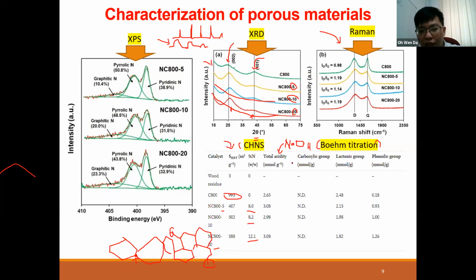And you also can look into carboxylic group, lactonic group, and phenolic group. So for all this, you have to change your base. For total acidity, we use sodium hydroxide. For carboxylic acid, lactonic group, or phenolic group, we use something else, maybe like sodium carbonate, and so on. So we use something else with a different strength, different basicity. NaOH is a very strong base. That's why we use it to neutralize all the acidic group on the adsorbent. So you can choose other things, and from there you can deduce what are the amount of lactonic group that you have, what are the amount of phenolic group that you have, and so on.